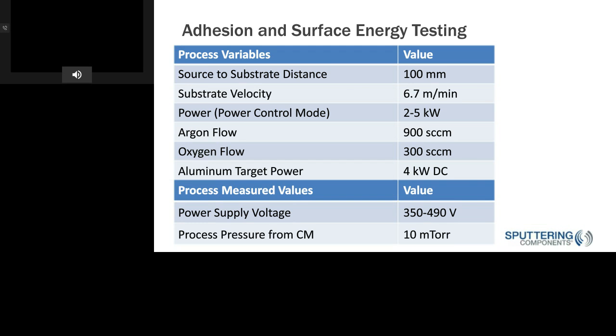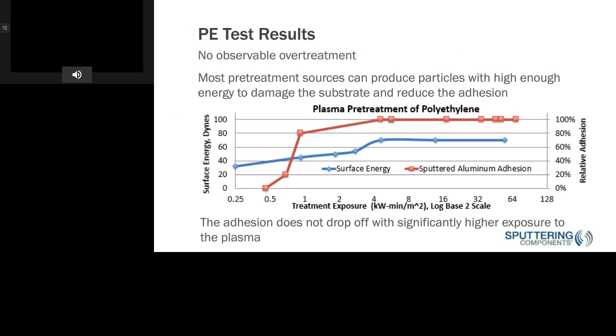So here I've got three graphs showing some results. The first graph here was plasma pretreatment of polyethylene. You've got the treatment exposure on the x-axis and the surface energy on the y-axis, and adhesion on the y-axis too. So the blue line is the surface energy and the red line is the sputtered aluminum adhesion. So you can see with increased exposure time, the aluminum adhered much better to the film. And there was no observable overtreatment. We've mentioned that most sources can produce particles with high energy, and we didn't observe any overtreatment here, and the adhesion didn't drop off with significantly higher exposure.